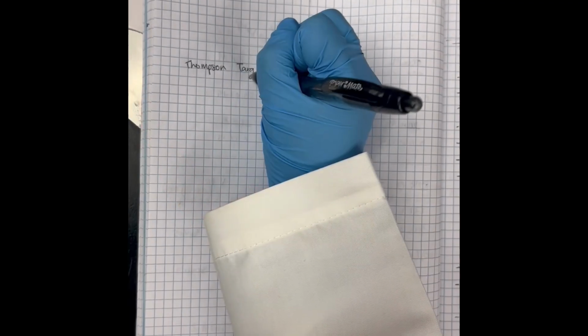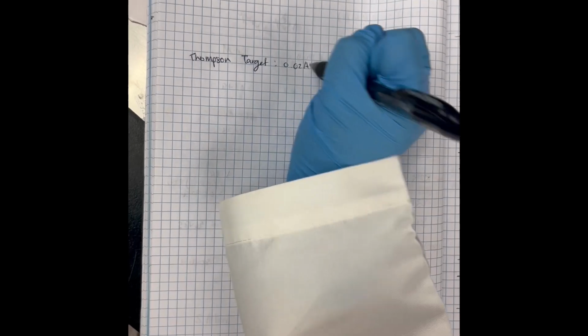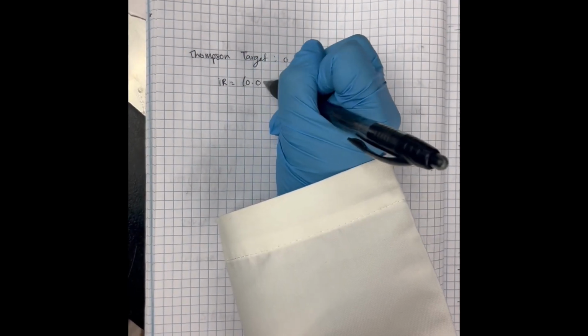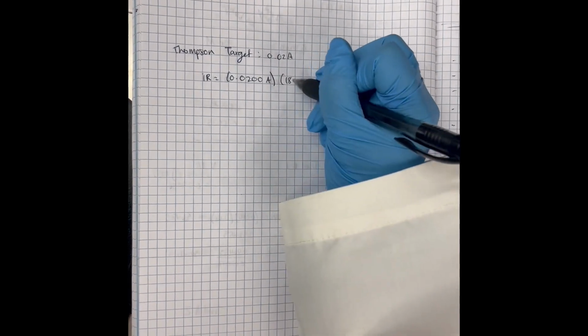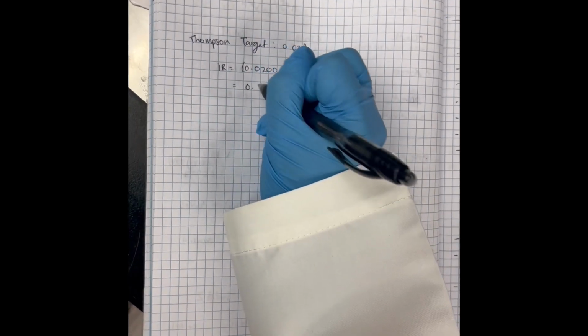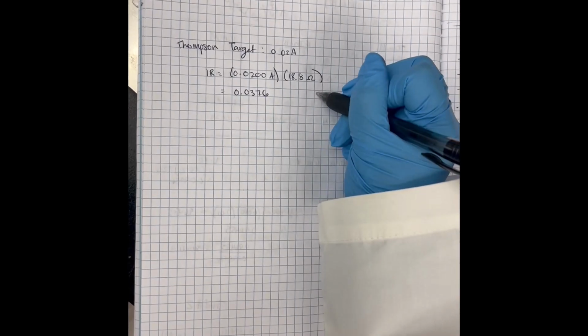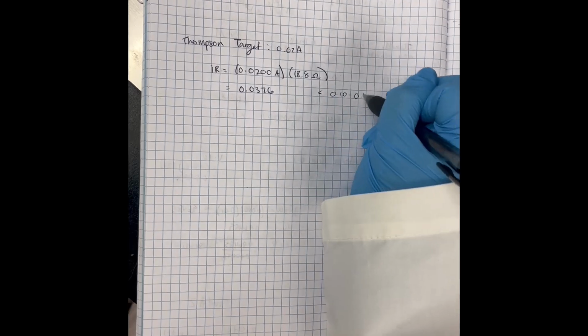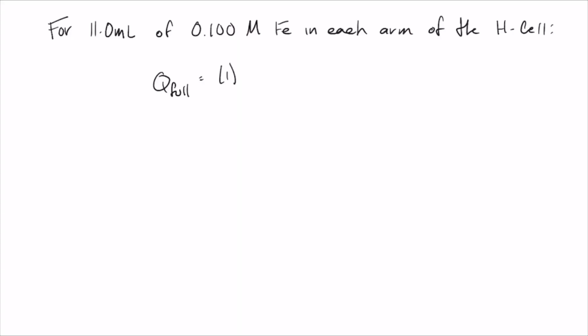Following our reference data, we used a 20 mA current in our IR loss calculation. We multiplied our current by our experimental resistance to get around a 0.04 voltage drop, which was well below our 0.10 to 0.15 voltage limit. The anodic time used in our experiment was calculated using Faraday's law based on a single electron redox event, a 0.1 molar concentration, and an 11 milliliter volume, resulting in a full theoretical capacity of 106.1 coulombs.